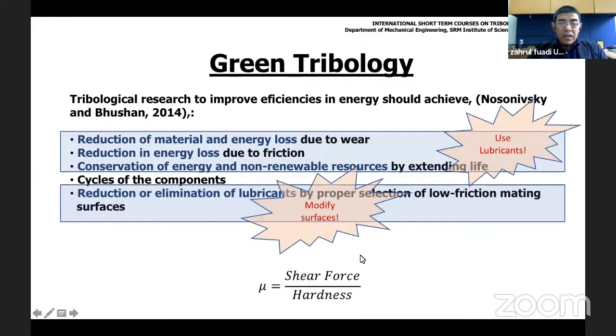If you see this equation here, this is taken from Hutchings' book, the coefficient of friction is shear force divided by hardness. So if you want to reduce the friction, you need to reduce the shear force, which means that you use lubricants, or you can use a harder mating surface, increasing the hardness. For example, you use a coating, you modify the surface, but you don't know which one will work. But we hear and we see and we find out that the friction reduction is caused by the combination of lubricant and lubrication and surface modification.